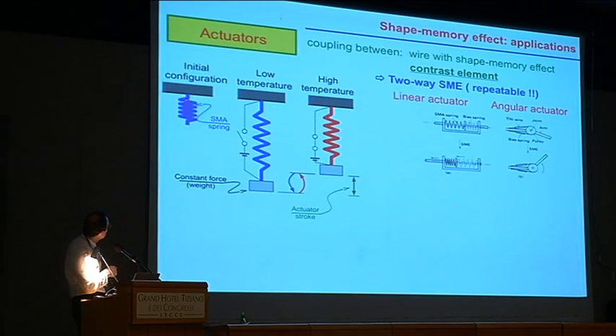And for example, we can look at this picture here. So if you start from a spring, now I consider a spring which is short, you apply a load on this spring and it gets elongated, so it gets a much longer spring. And if you keep the weight constant and heat up the material, for example, through some joule effect, the spring tries to go back, but due to the presence of the weight, it is not able to completely go back, so at least it's shortened a little bit. When you heat it up, it goes from this configuration to this configuration, but when you cool it down, due to the action of the weight, it goes back here.